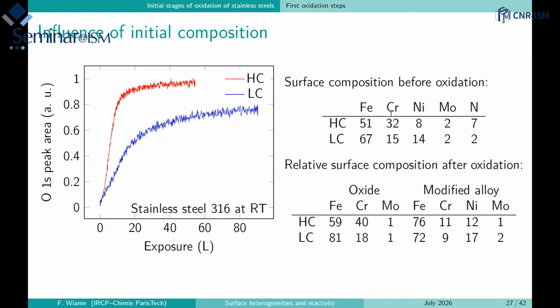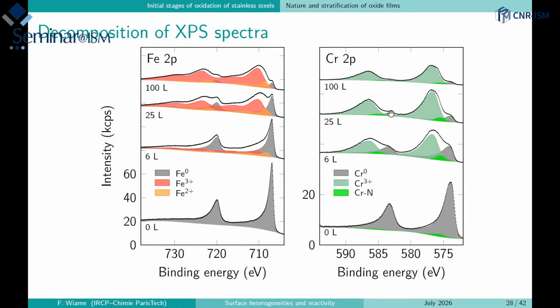If we are looking now more deeply at the analysis of the photoemission spectra, we can, at different exposures, look at the composition of the surface. We can identify, in the case of iron, two different oxidation states, the +2 and +3 oxidation states of the iron. And we can also identify the +3 oxidation state of the chromium. And as we have said, there is some chromium nitride at the surface.